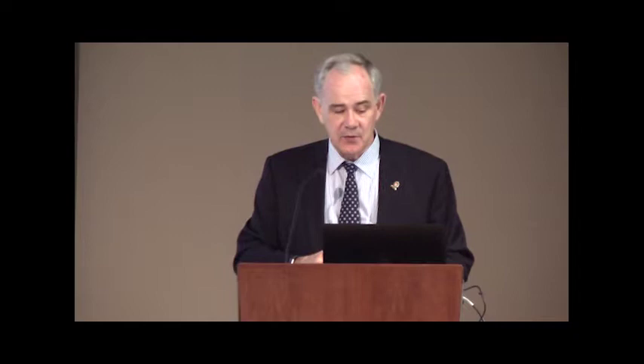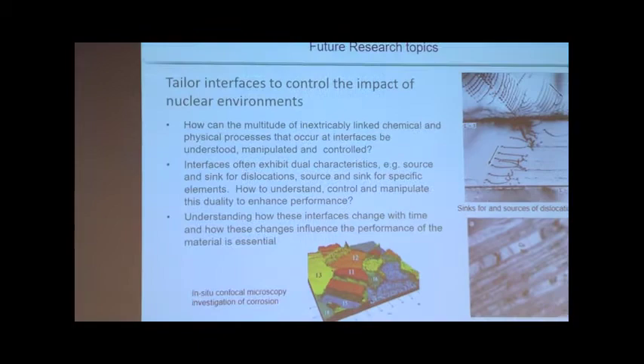One of the other things that was clear is that we are inventing new tools and new capabilities to explore different types of reactions that are important. The image in the center is an example from corrosion, but this time it's in situ confocal microscopy — the grains have been artificially colored. Again, what you notice is that each grain has been consumed at a very different rate. Why is that? We don't understand what controls it, but it's something that we need to figure out.